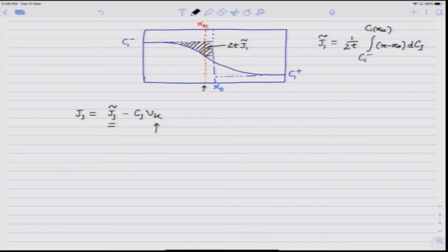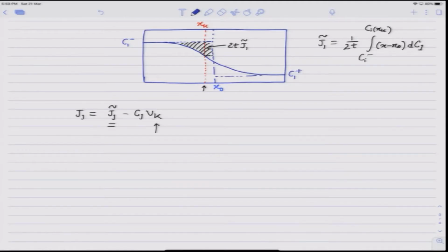Now these marker planes are usually travelling at a constant composition, and in an infinite diffusion couple we know each composition plane is moving parabolically with time. In other words, we say C is a function of x over root t, where x over root t is the Boltzmann parameter lambda.